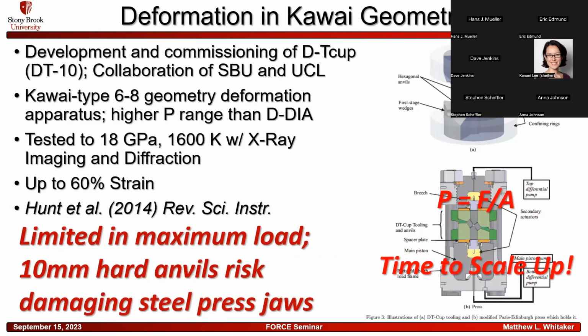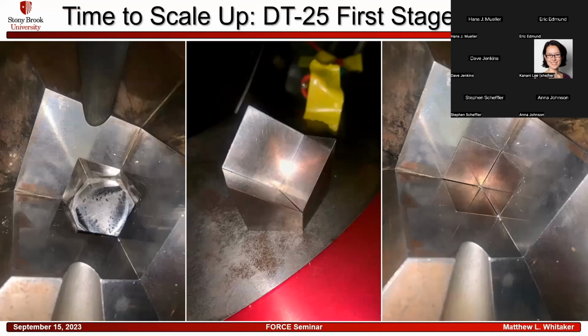However, one of the issues that we ran into with this device is that we were limited in the maximum load, because the 10 millimeter hard anvils risk damaging the steel press jaws that are forcing everything together. So again, pressure is force divided by area. We needed to scale it up to make higher loads achievable. So we scaled it up to the DT25, where 25 just means it's 25 millimeters on the edge of the cubic anvils that we use.